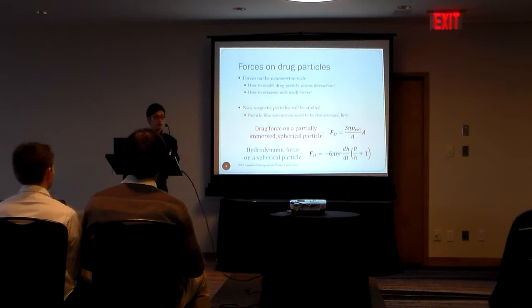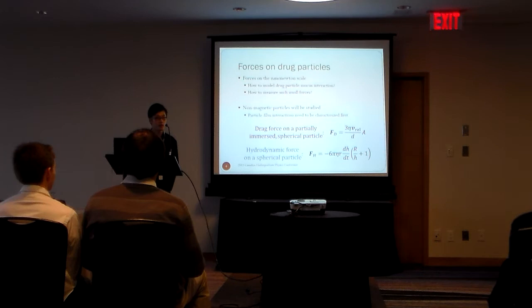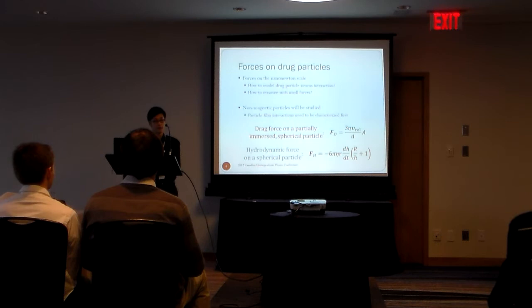A follow-up question asked about the liquid film proxy: we're not looking at actual mucus, but using a silicone oil that's been cross-linked. We did rheological measurements on sample mucus and also on our cross-linked film, and they agreed, so we can concretely say that our film is very similar to mucus.